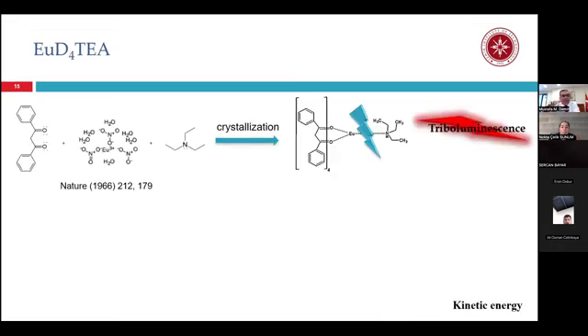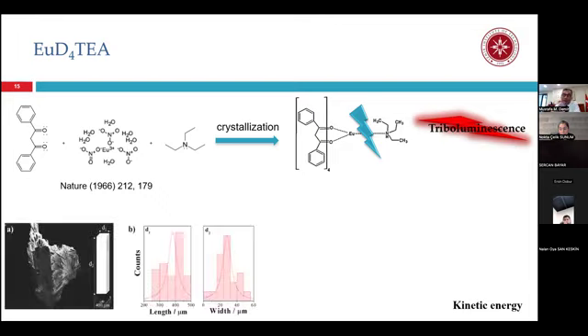The synthesis has been known for more than, say, 50 years. We begin with 1,3-diphenyl-1,3-propanedione, then use europium nitrate and triethylammonium. We mix them, and they undergo crystallization at low temperature. Then we have an organometallic compound. Europium is at the center. The central europium atom is surrounded by ligands. And pay attention, the distance between europium and nitrogen is quite long, around 2.5 angstrom. Remember that the carbon-carbon bond is 1.4 angstrom. It is quite long compared to the carbon-carbon bond.